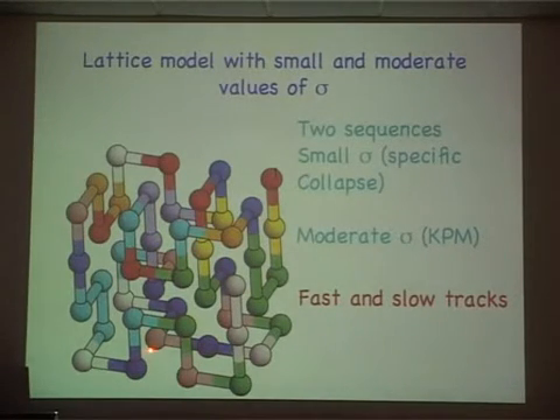So this is a lattice model. I think it's a maximally compact structure. It's the vertices of a three-dimensional cube, 3 by 3 by 4. And these various balls in different colors represent different models for the residues. This defines a particular sequence. And this sequence will fold reversibly to this over and over again. You can change the sequence and still retain the same quote-unquote ground state. And you can then also make that fold as well.